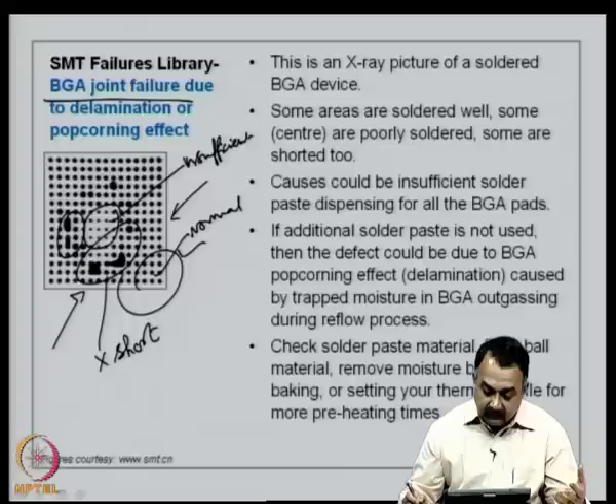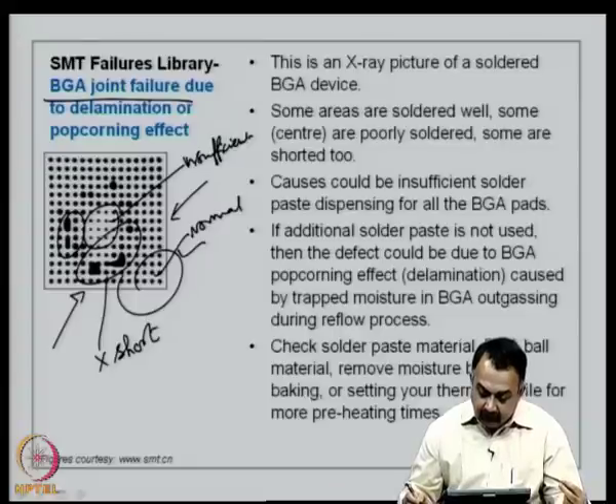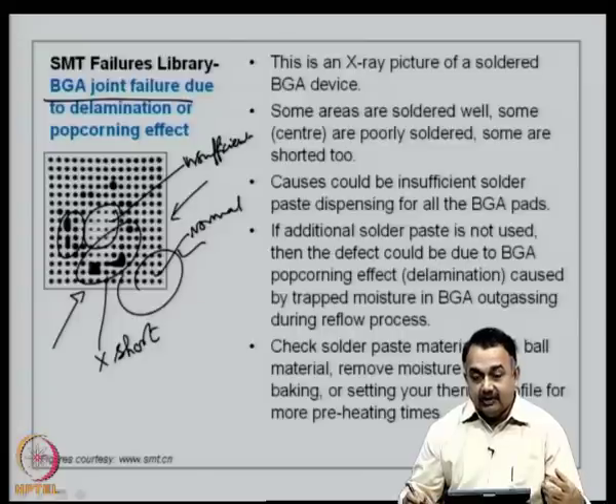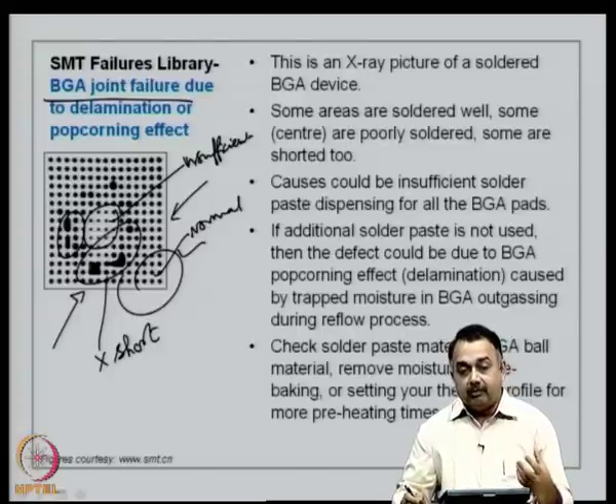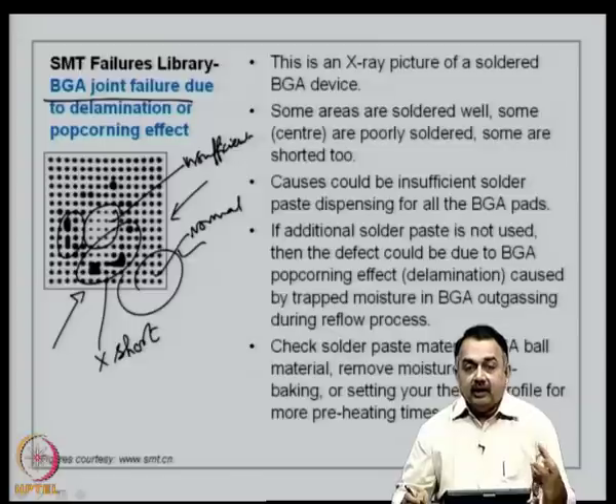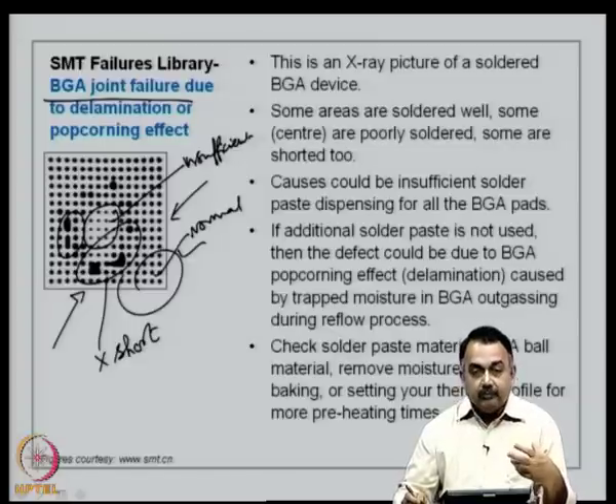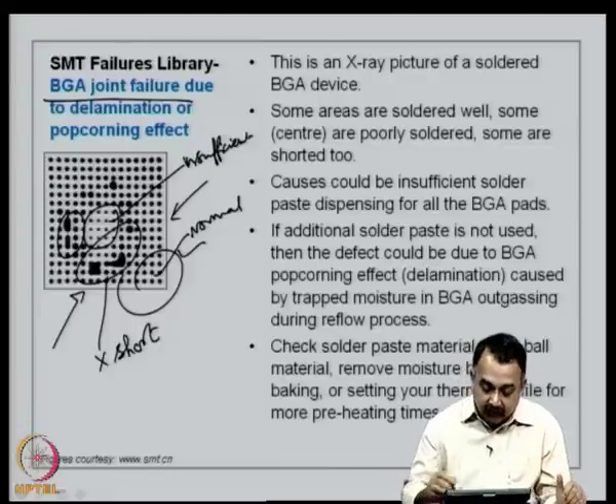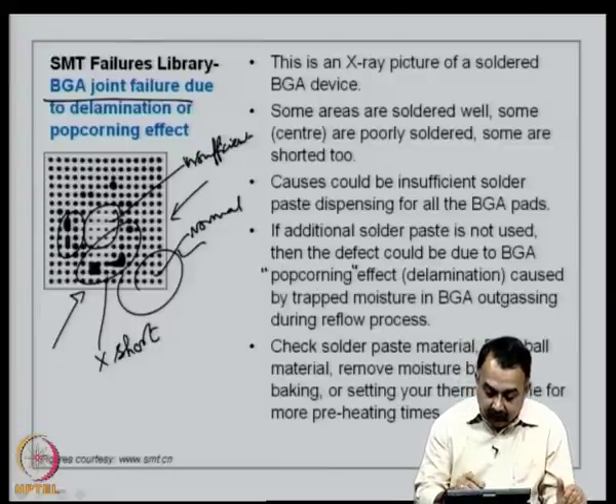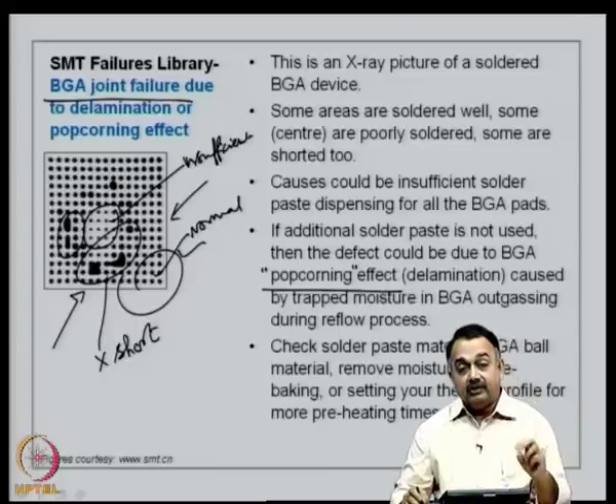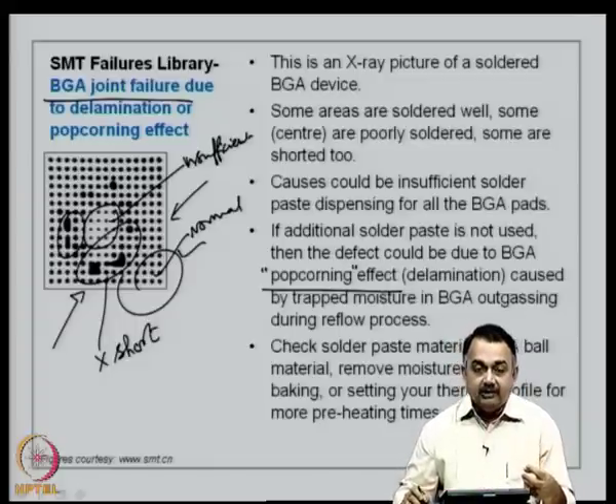Either the solder paste has not been dispensed properly, if you are using solder paste to attach a BGA. If you have not used additional solder paste for attaching a BGA, that means you are using the BGA solder ball itself to reflow and then form an interconnect to the board, then this could be due to a delamination or popcorning effect, as you call it, very common in BGAs. Again, this is due to the plastic body of the BGA absorbing moisture.